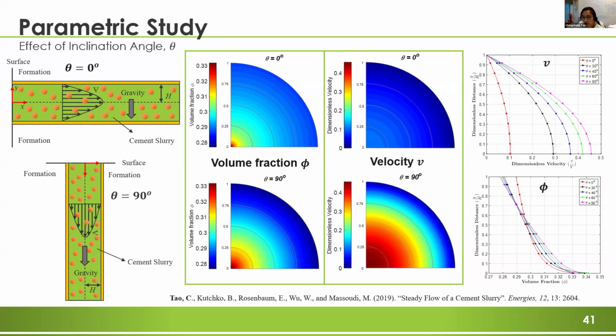So from the two figures on the right, the velocity shows a parabolic distribution and the particles tend to concentrate at the center. Larger values of theta result in faster flow. When the plates are inclined at a sharper angle from horizontal to vertical, the particles tend to move faster and have lower concentration at the plates.